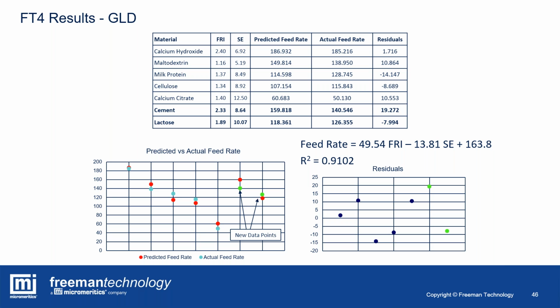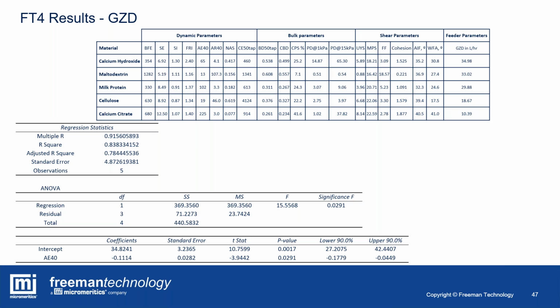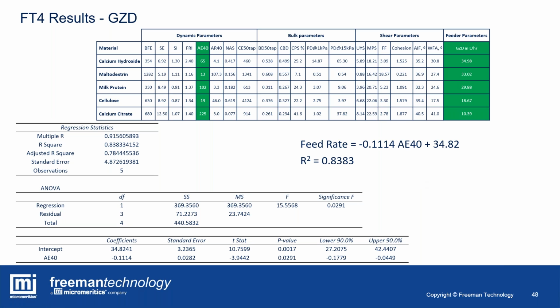When we did the same thing for the twin screw, we of course had the same material properties as measured by the FT4, but you had very different volumetric displacements because of the scale and the configuration. That was intentionally much lower throughputs, a more precise process typically, but again, a 3.5 to 1 type performance. And interestingly, in this case, it was the aeration characteristic that proved to be most relevant. And here we can see again an 83% R squared value, suggesting that this was a robust prediction.